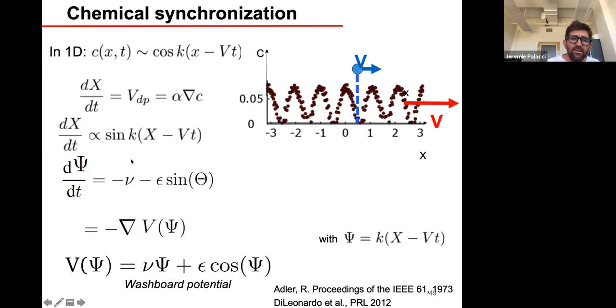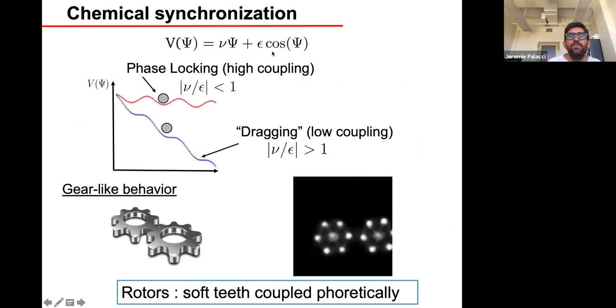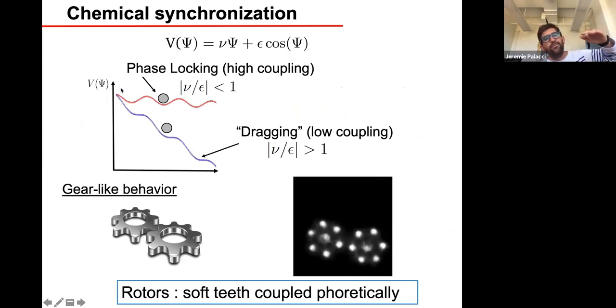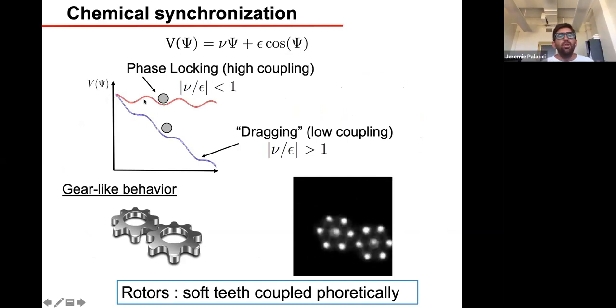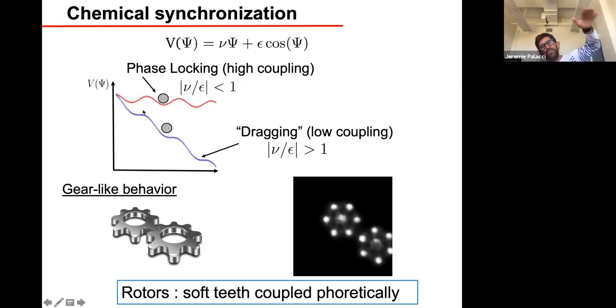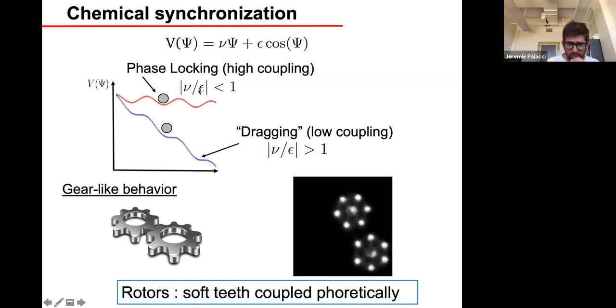And what we get is that the phase of the system is going to be in a potential, which is a washboard potential. And so it's nu psi plus epsilon cos psi. So we see there's two solutions. If the washboard potential is not very slanted, which is that situation, then the particle will just fall down in this potential and stay there. You're in the synchronized state. On the other hand, if you have low coupling, so nu over epsilon is large, then the particle would just fall down this corrugated path, and that's what we observe for co-rotation.